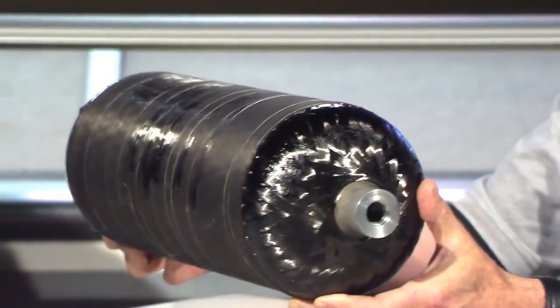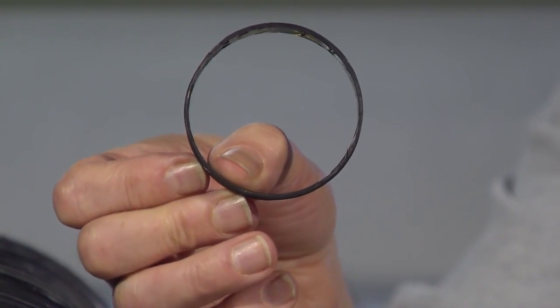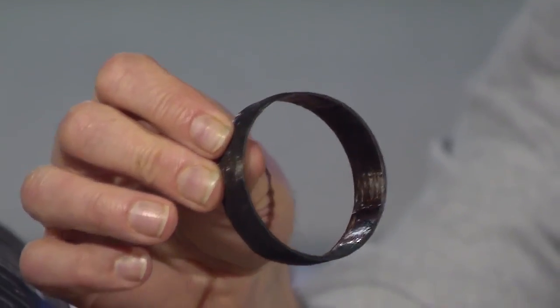The small sample helped us, but we're going to do some more testing. We're going to shortly put these into a liquid nitrogen environment, submerge them in there, and test them to failure. Here's one without a liner that we made — just a section from it. We've tossed these into liquid nitrogen, corrosive liquid oxygen, and very cold liquid hydrogen, which are of course the fuels that power a lot of our rockets. When we took these out and put them under high-powered microscopes, we saw no cracking, no delamination — it came out as it went in.